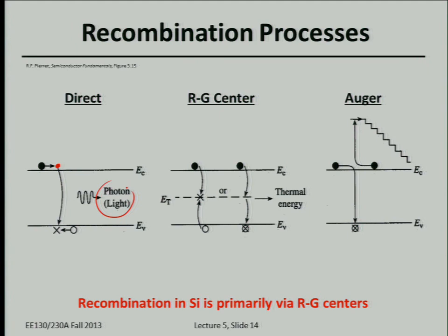Most likely, this is based on the material properties. I would say, in silicon, in most cases this process doesn't involve photon emission. They don't shine light, they just heat the lattice. So that involves a heating process rather than shining light. That's the case for silicon.